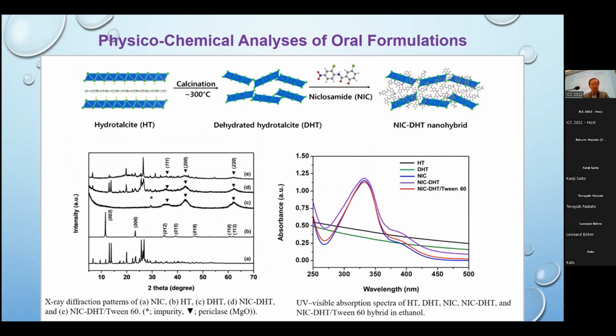So in order to overcome such disadvantages of niclosamide, namely very low solubility and bioavailability, we have developed a new drug delivery system based on layered double hydroxide, namely hydrotalcite, as a carrier. Based on the synthetic scheme above, LDH was first calcined at 300 degrees C. Actually, we also performed the same experiment with LDH only, but the solubility was not well solved. That's why we calcined at 300 degrees C to induce porous dehydrated hydrotalcite, where niclosamide was coated on it to form a niclosamide DHT hybrid.